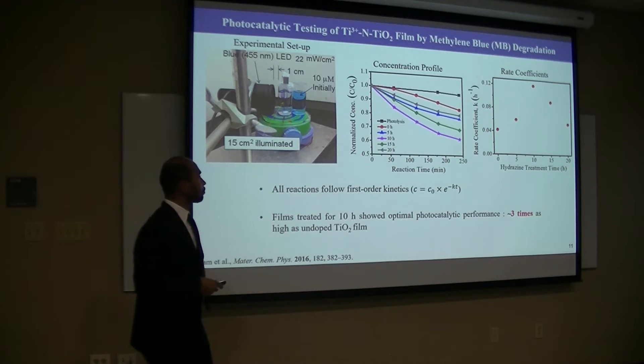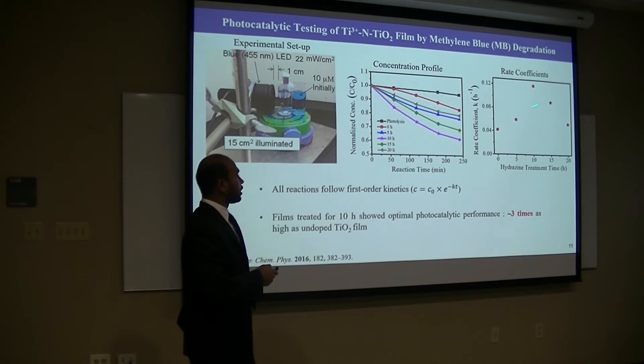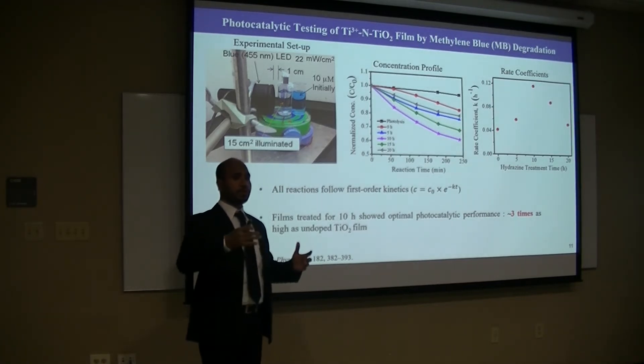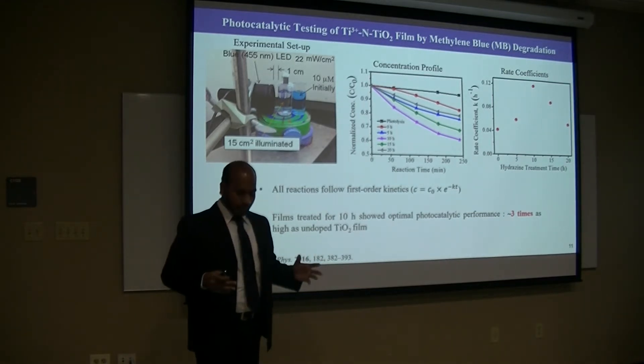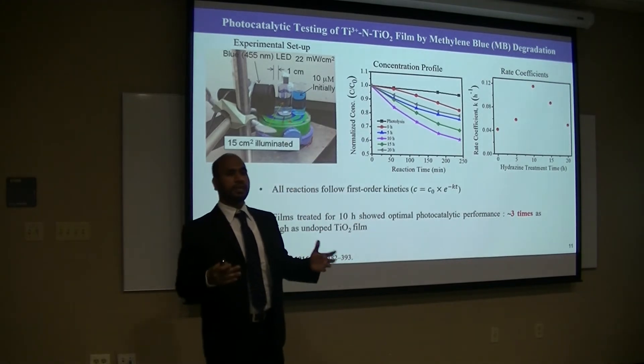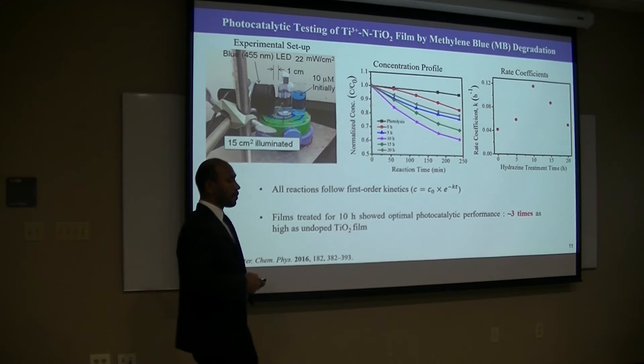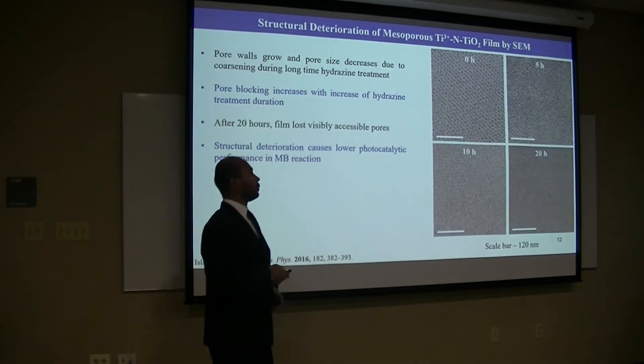However, when we increase the hydrazine treatment time beyond 10 hours, the rate coefficient decreases. Hypothetically, it is supposed to keep increasing, but it does not. Visible light absorption is important, and at the same time surface area is very important for reactions. We think that long-time hydrazine treatment might cause trouble with the nanostructure, which was characterized by SEM.